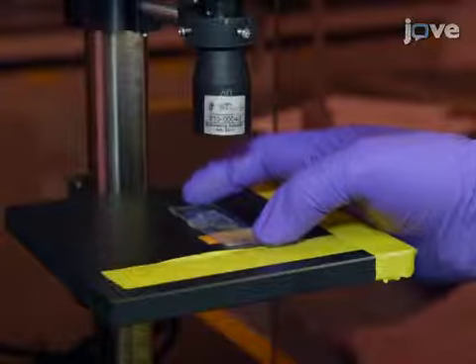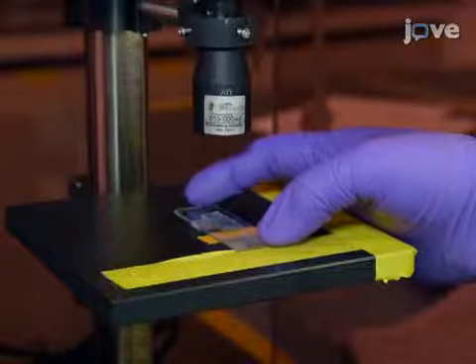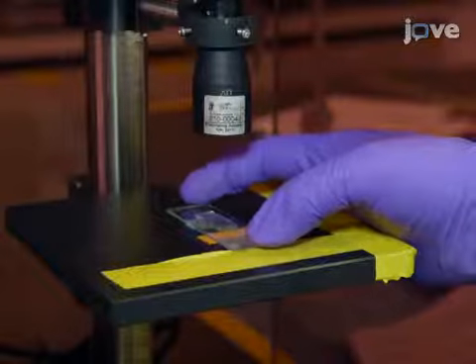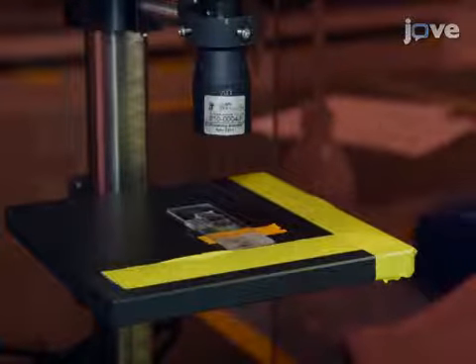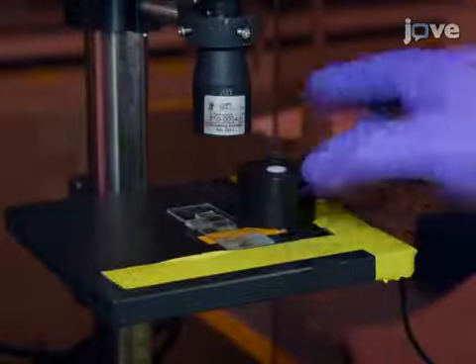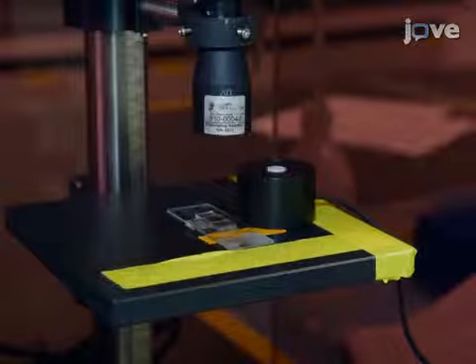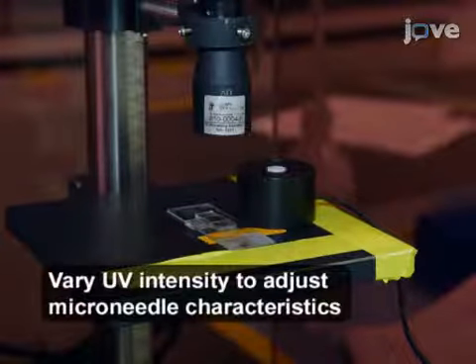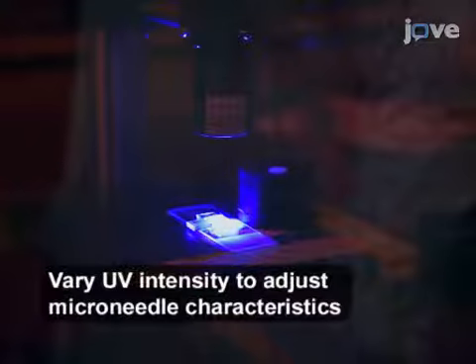Then, place the setup into a UV curing station and place a radiometer next to the setup to measure the intensity of the UV light. Irradiate the setup with high-intensity UV light between 320 and 500 nanometers for 1 second at a distance of 3.5 centimeters from the UV source.